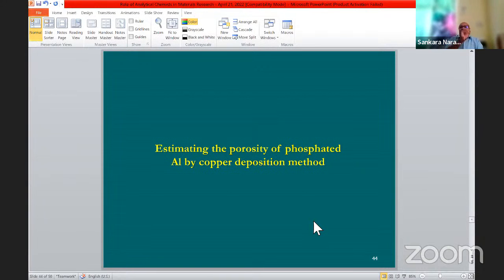So where are the uncoated areas? You can count the number of blue spots, and you can tell how much porosity is there. If some area is not coated properly, it will appear as a blue patch. So you can see the coating uniformity, how much porosity is there, whether small pores or bigger pores are there, and the uniformity of pore size. It is a very simple method.